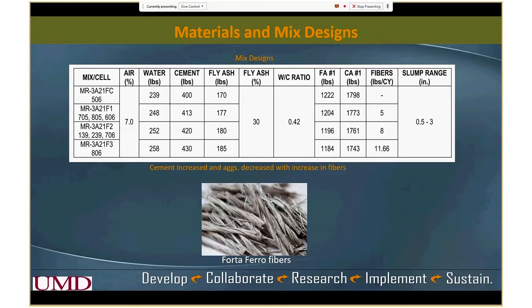With the increase of the cement and the fiber volume added, they had to do something with the aggregate. So you can see on the right side of the table that they decreased the fine aggregate basically, and also a little bit of coarse aggregate. The slump was 0.5 to 3. And the picture here shows the fiber that was used. Next slide, please.